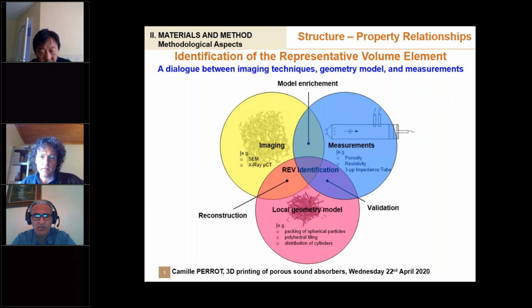My point is that in a way this is the idealistic situation, and you will probably see during the talks of the other speakers that there is always a kind of adjustment to be done when comparing measurements with macroscopic parameters obtained from the local geometry model. And this comparison is fruitful, because the transport parameters convey some physical information, and by interpreting this physical information correctly, you can go back to imaging techniques and see if you missed at first sight a microstructural feature which has a significant impact, and then you can adjust your model.